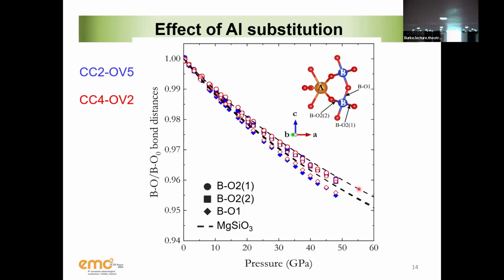In the case of MgSiO3, the end member, these are the black dashed lines. You have quite anisotropic compression, but BO1, the apical one, is practically identical to the longest BO2, and all three distances start quite similar. In the case of the aluminum substitution, the one along the apical direction gets really, really much more compressible. So you have a difference between the basal and the apical ones.